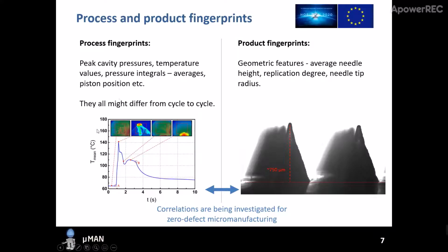As an example here, we used thermal imaging to extract the temperature of the polymer melt during ultrasonic micromolding. As you can see in this temperature profile, there are some distinct features like peak temperatures and maybe temperature integrals, the area under this curve. We could extract this information from cycle to cycle and try to correlate it with our final product quality, which is defined by our product fingerprints or geometric features.